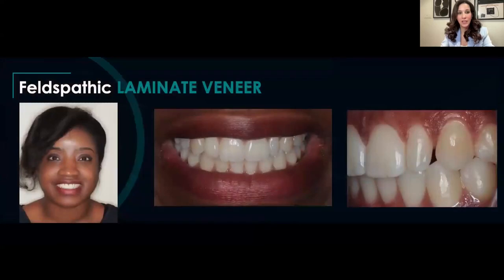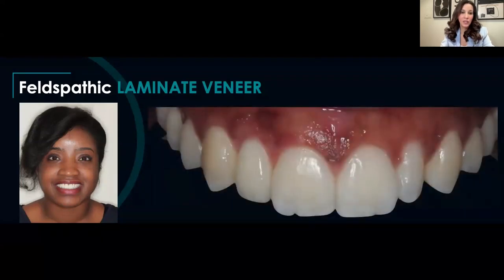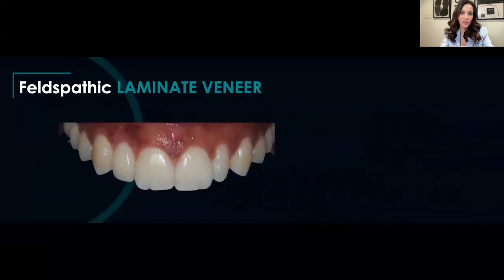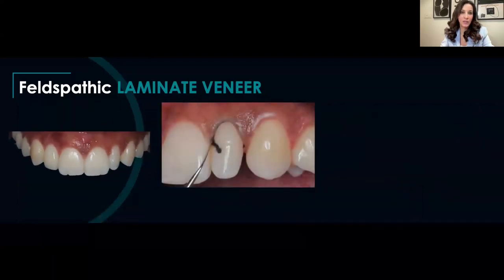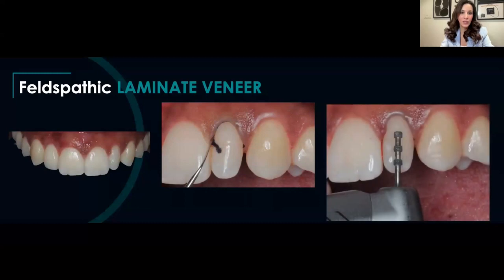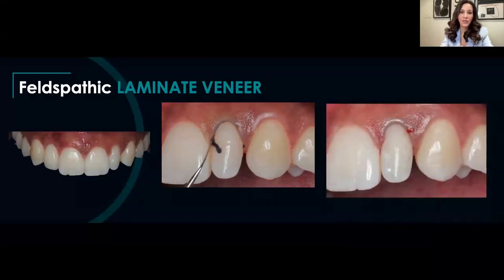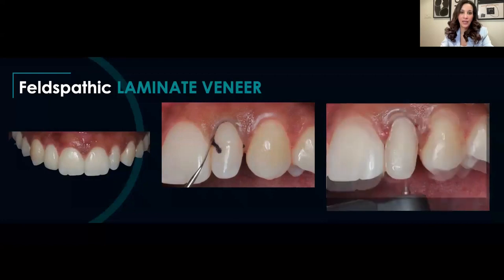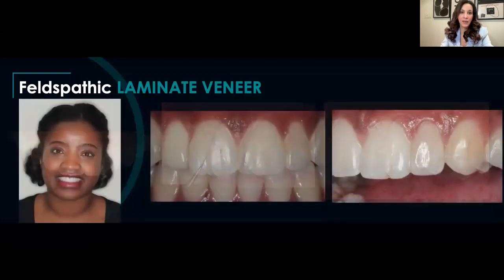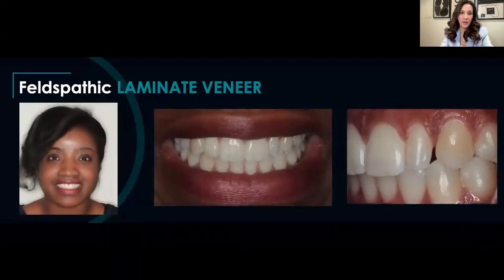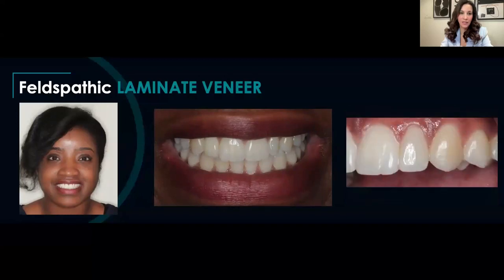Another example is a patient here who presents with a peg lateral. Very simply, a very conservative indirect restoration is to do a porcelain veneer where you can very predictably prepare the tooth. You can use depth reduction burrs, as the ones you see here, that reduce the enamel to 0.3 millimeters. We can then finish off the preparation and create a veneer that's made out of, in this case, a feldspathic material, which gives a very aesthetic outcome to the patient. And you can see that there.